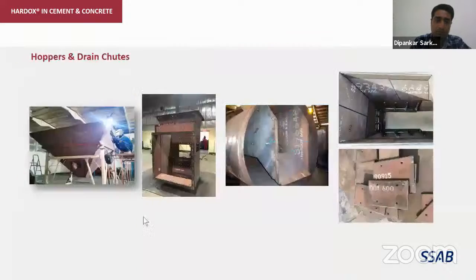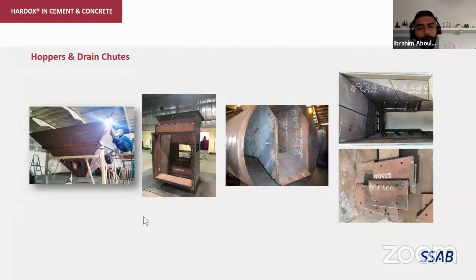Next slide, please. Then we get into the cement plant. We have a lot of hoppers and drain chutes, and in that case, they are regularly exposed to high flow, pressure, and impact. And using Hardox to fight the wear and abrasion will extend the service life and improve the performance of your chutes and hoppers. Grades that can be used depending on the impact. You can use Hardox 500 tough. If it's more or less sliding wear, we recommend directly Hardox 600 in order to extend the service life as much as possible.